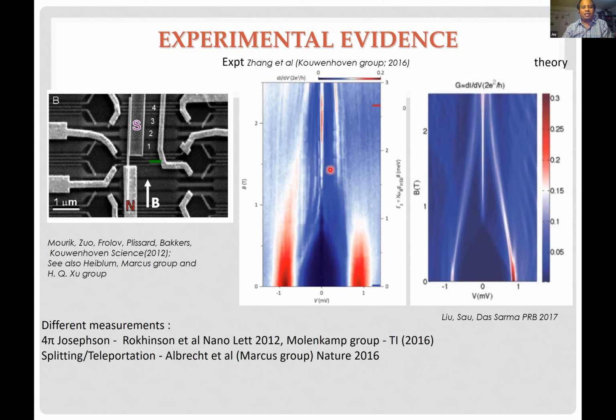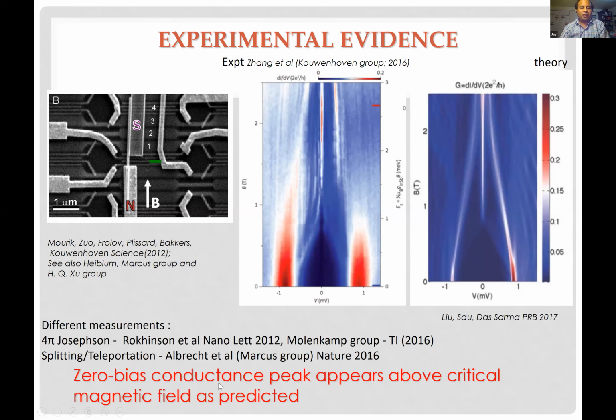What you don't see, and what is not inconsistent with the simulation here, is any sign of a gap reopening. The bulk gap is actually reopening in the theory, it's just not accessible from the end. That's the problem. There are a few other measurements that I'll tell you about in a bit, the 4-pi Josephson effect and so on, which show other aspects of Majorana fermions. But the good news is that you see a zero bias conductance peak above the critical magnetic field as predicted. The bad news is that you don't see the gap closure and reopening. So we need to look for more signatures.